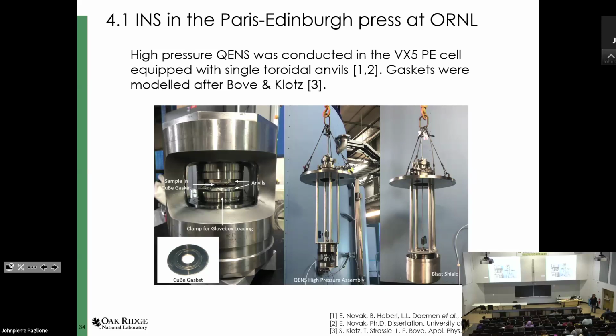What are the materials here? Of the pot or the cell? The pot is aluminum. The cell itself, this here is all steel. The anvils in this experiment are cubic boron nitride, and the gasket was copper beryllium. But typically a Paris-Edinburgh cell would use TiZr gaskets because they are using that isotopic mix where you have a null scattering gasket without any Bragg peaks. At ISIS, they have some of these Paris-Edinburgh cells that are entirely made from copper beryllium. So they exist, but we don't have those.